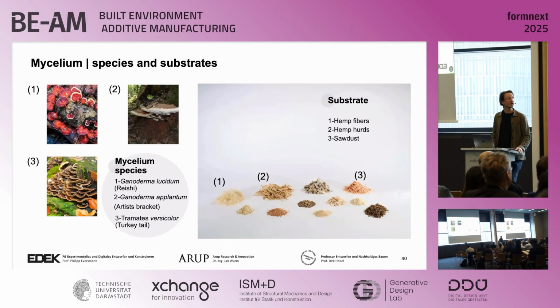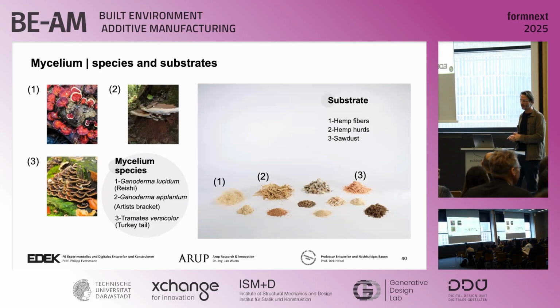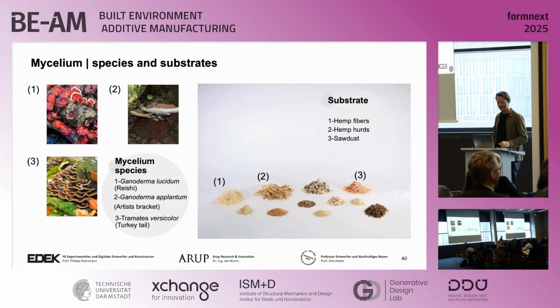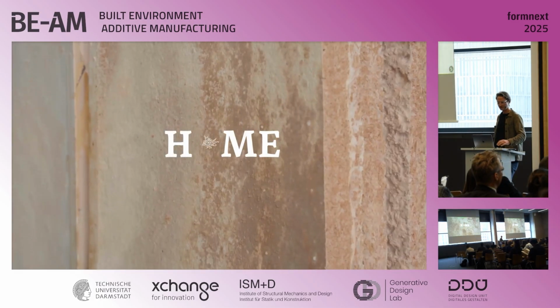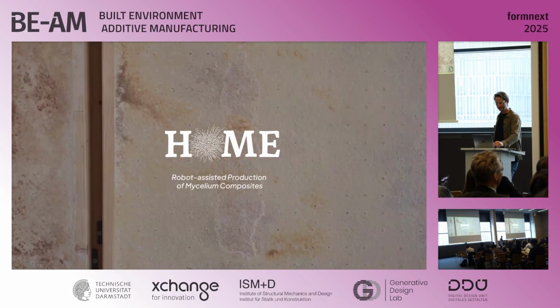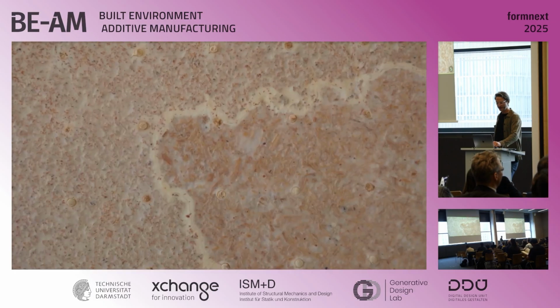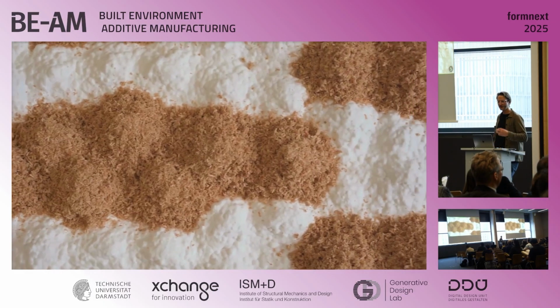We used the reishi mushroom, Ganoderma lucidum, because it can grow on timber and has quite a high resistance to contamination. We also vary the types of substrates we use, because you can achieve quite different material properties, especially for the acoustics. Here is a short film showing a bit how that works.